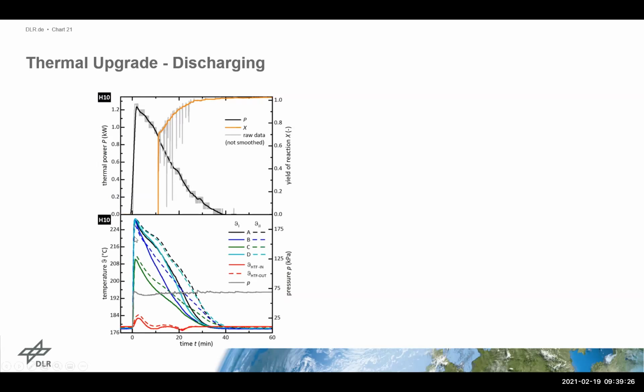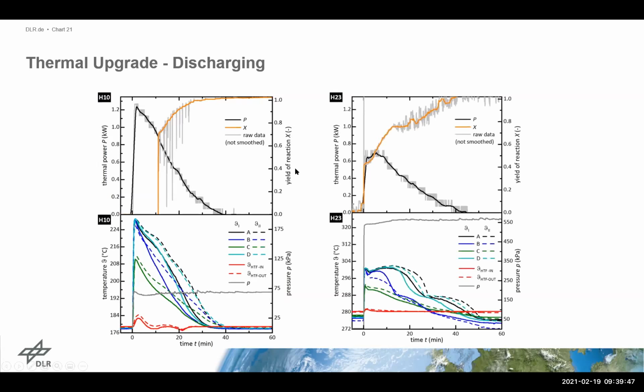You see immediately the exothermal reaction is initiated as soon as the valve is opened. We have more or less a temperature jump here, and this results, of course, in, again, 1.2 kilowatt of thermal power during the discharging process. It's even so fast that our measurement was a bit interrupted here and didn't work that properly in this moment.